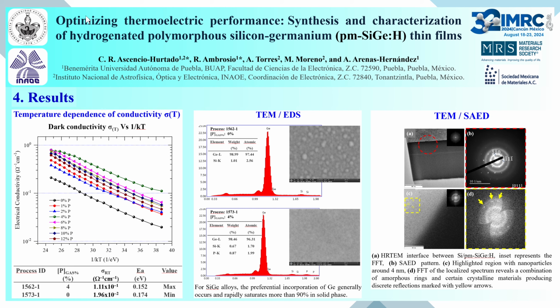However, applying fast Fourier transforms in reduced regions where an evident contrast change is detectable will display a spectrum with crystalline samples. In other words, the fast Fourier transform displays well-defined reflections at ~0.17 nanometers, meaning a reflection at the 200 interplanar spacing of the 50-50 alloy. At the same region, nanoparticles of about 4 nanometers in size are visible where localized contrast change is evident.